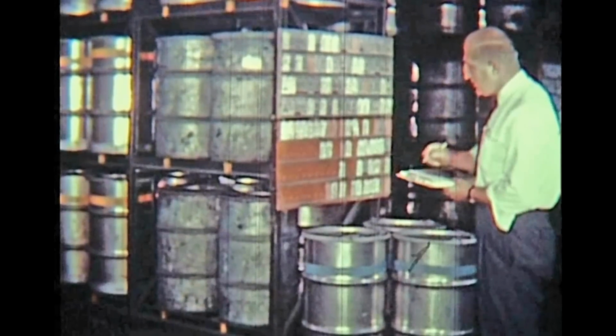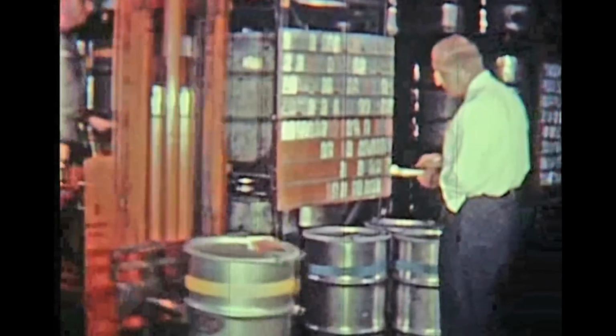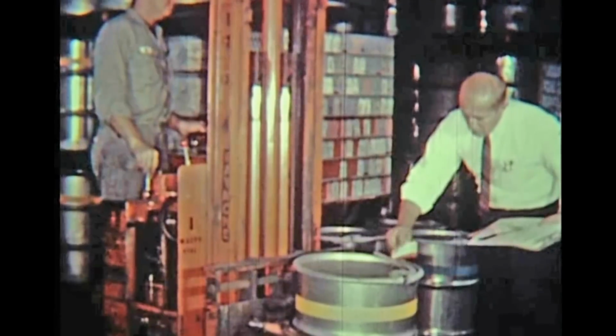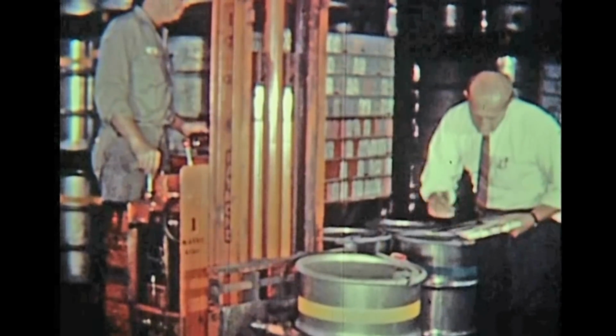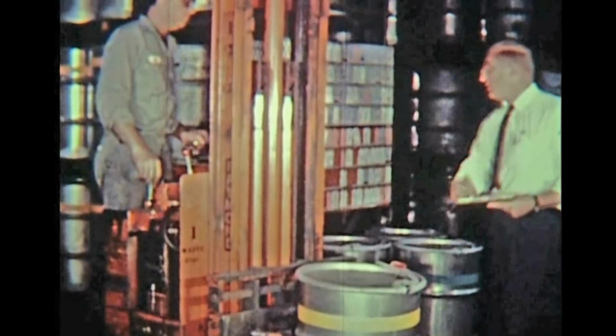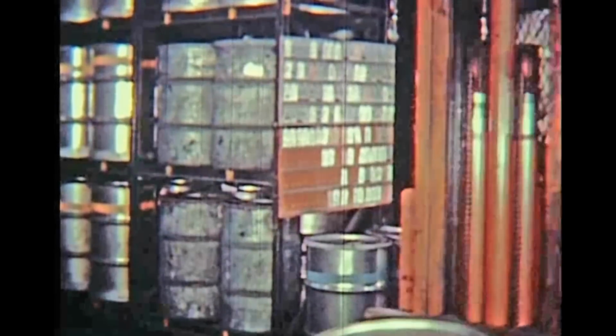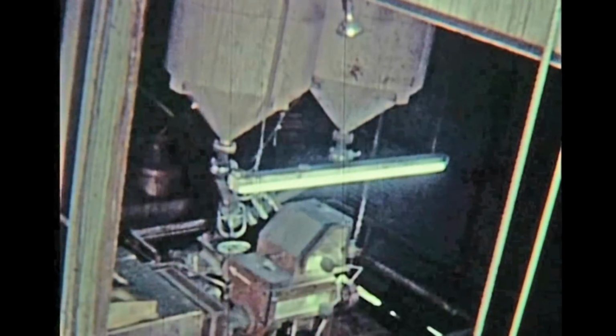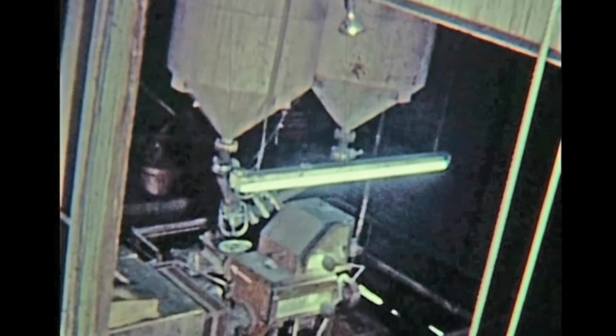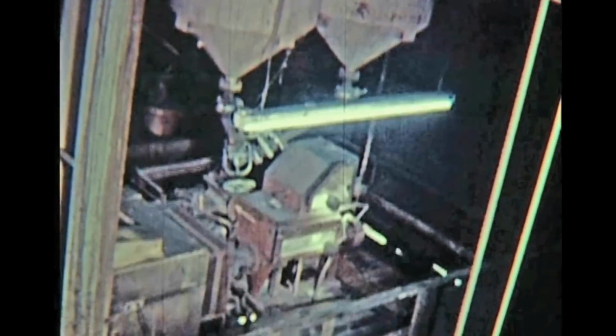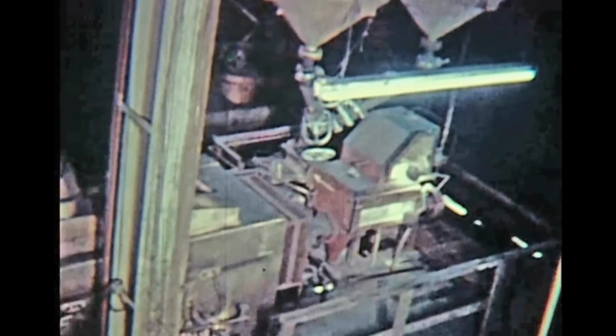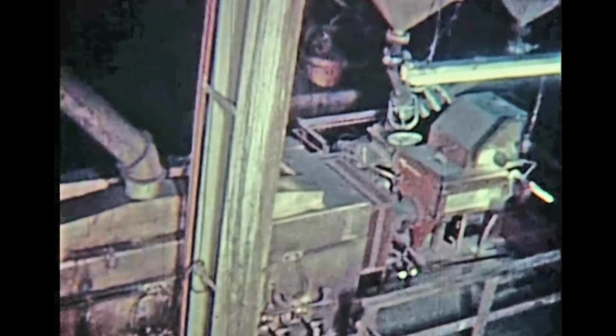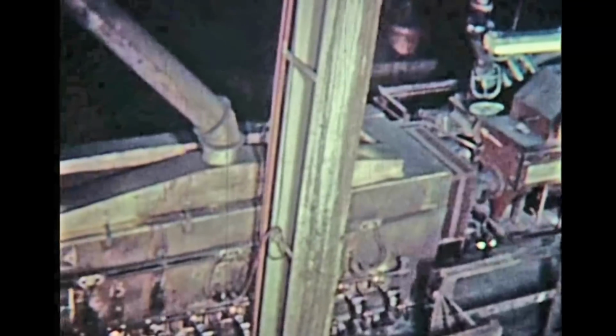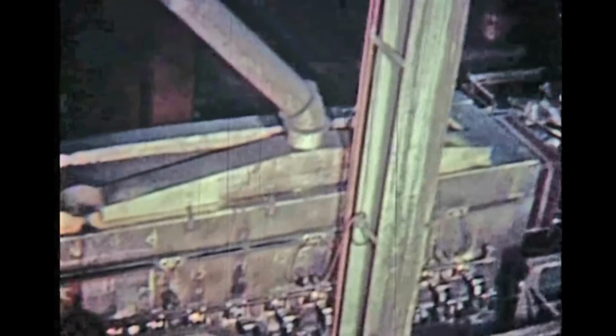Selection of the particular batch to be used for the 218 non-sag wire process is based on the purity check. While all the crystals must meet specifications, only the purest available are used for 218. These crystals are partially reduced in the rotary furnace. By varying the feed, temperature, and pressure of the gas inside the furnace, we convert the white crystals to blue, purple, or brown oxide. A 24-hour run is called a batch.